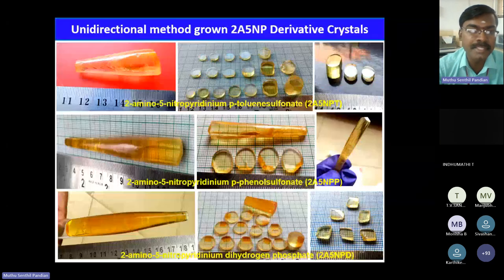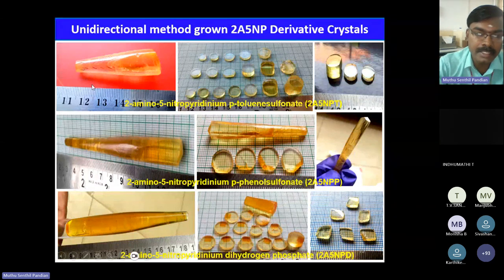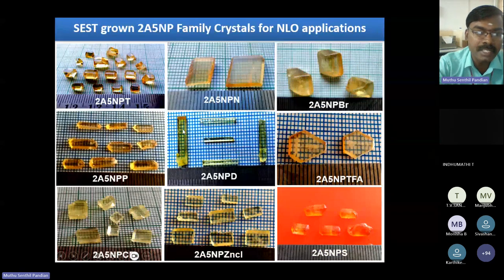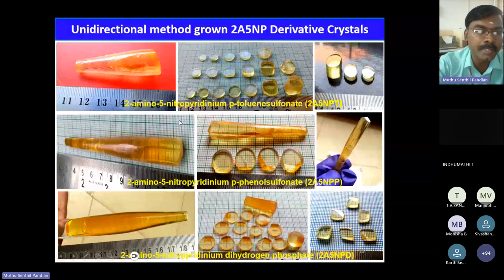But in the case of the SR method, what we have done is we cut the crystal from the conventional method and mount it at the bottom of this glass ampoule, and then we pour the saturated solution inside the glass ampoule, and apply temperature at the top and bottom portions. The temperature at the top is only for solvent evaporation. When the solvent is evaporated at the top of the solution, the remaining solid particles approach the bottom of the glass ampoule, and the crystal will be grown like this.